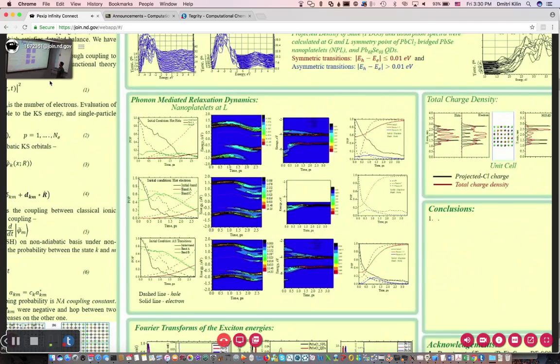Here it still gives us the same result: electrons relax slower than holes. Another thing is, in this green line I calculated the intermediate bands, LUMO+5 to LUMO+10. Initially it is populated with time, the electron population reaches its maximum at 1 picosecond, and then it starts to relax.